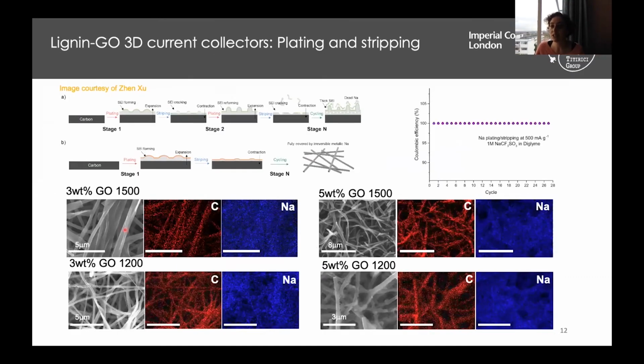So we checked what happened with these three-dimensional carbon structures after continuously plating and stripping, and we hypothesized that what is occurring is that there's a solid electrolyte interface being formed on top of our carbons that is stable and enables the homogeneous plating and stripping, and our fibers are fully covered with this metallic sodium. And we are avoiding an inhomogeneous formation of the SEI, which promotes the cracking and the formation of dead sodium, as this cartoon is showing here.